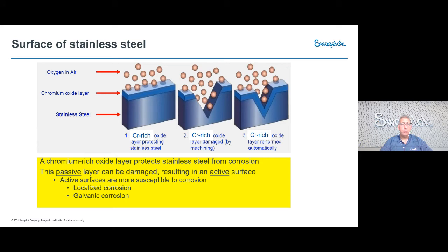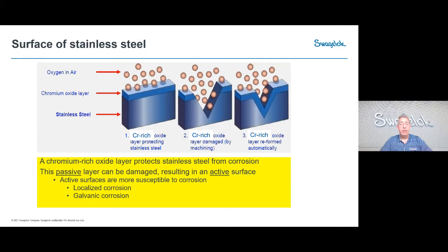How does adding chromium to iron make it stainless? Because there's enough chromium in the base material and a source of oxygen in the environment, it forms a chromium-rich oxide film on the surface. That silvery metallic-looking stainless steel actually has a very thin but transparent passive film of chromium-rich oxide providing rust resistance. However, if you damage that film, it will reform as long as the substrate has enough chromium and the environment has a source of oxygen — but in some applications this can be difficult to maintain.